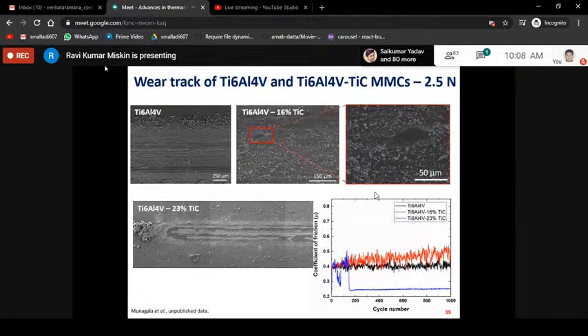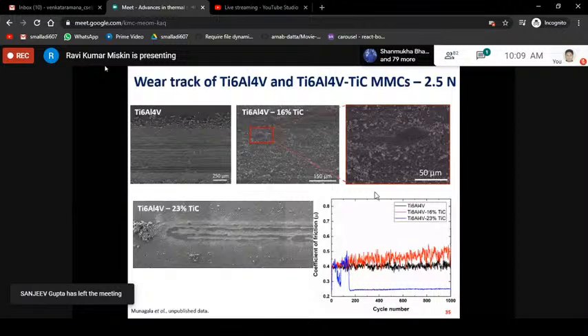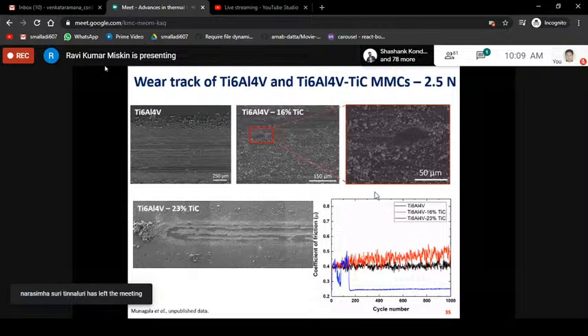Next. Yeah, so that's why you're seeing a friction drop in 23. As you can see in the blue curve, that is our 23% titanium carbide coating. You see a drop, it's actually going to 0.25. That's because initially you wear, but then you form these layers. As soon as you form these layers, you see a drop, and then it goes from there. Next.